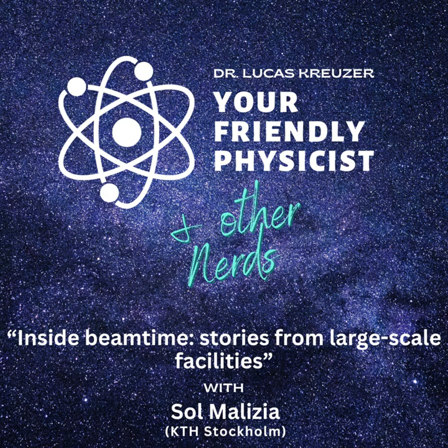Do neutrons damage the samples? No, they don't. That's a good thing. Yes, that's what we like also about neutrons. They don't interact with our sample like X-rays do. For example, my cellulose films, if we expose them to X-rays for a long time, they will just burn, they will just carbonize. That doesn't happen with neutrons. We can just measure and measure and measure for hours, and nothing happens. Neutrons are very gentle to your samples. They don't damage anything.